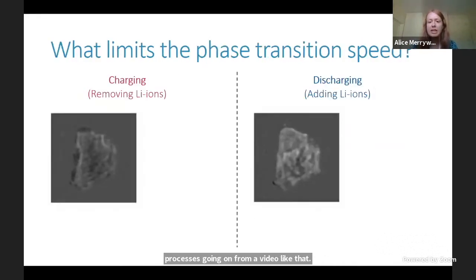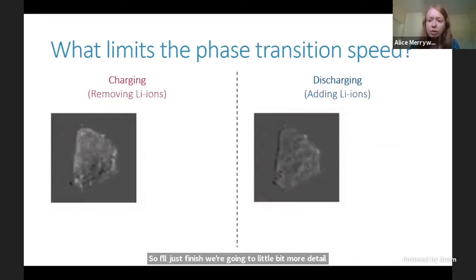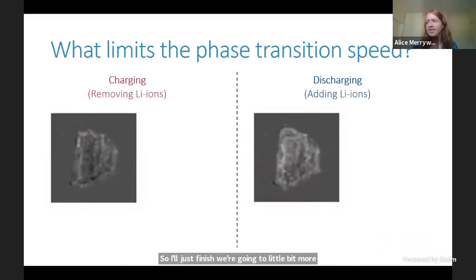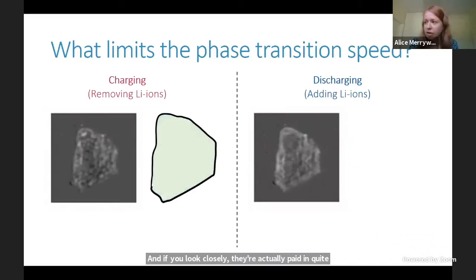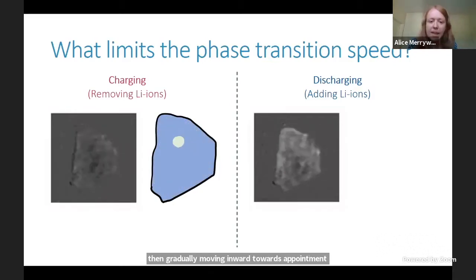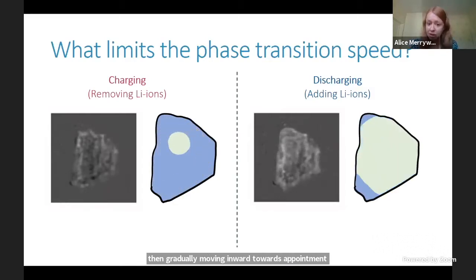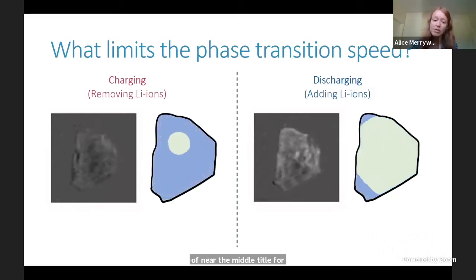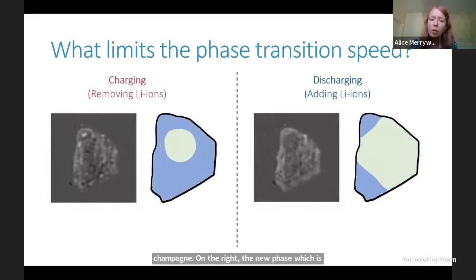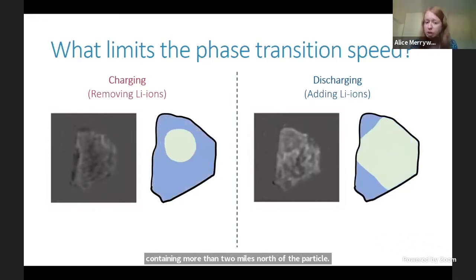So I'll just finish by going into a little bit more detail about those moving parts that we saw, which was a phase transition. So as you can see here, I've just taken those little parts of the video with the phase transition for the charging on the left and for the discharging on the right. And if you look closely, they're actually behaving quite differently. So for the charging on the left, hopefully you can see that that new phase, which contains less lithium ions, is starting to form all around the edges of the particle and then gradually moving inwards towards a point near the middle. However, for the discharging on the right, the new phase, which is containing more lithium ions than the rest of the particle, just starts forming at one corner of the particle and spreads out across the particle from just that one corner.